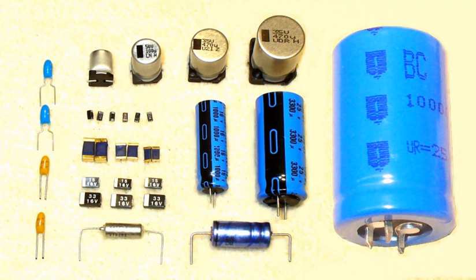His invention was supported by R. J. Millard, who introduced the reform step in 1955, a significant improvement in which the dielectric of the capacitor was repaired after each dip and convert cycle of manganese dioxide deposition, which dramatically reduced the leakage current of the finished capacitors. Although solid tantalum capacitors offered lower ESR and leakage current values than the aluminum E-caps, in 2000 a price shock for tantalum dramatically reduced the applications of tantalum E-caps, especially in the entertainment industry. The industry switched back to using aluminum electrolytic capacitors.